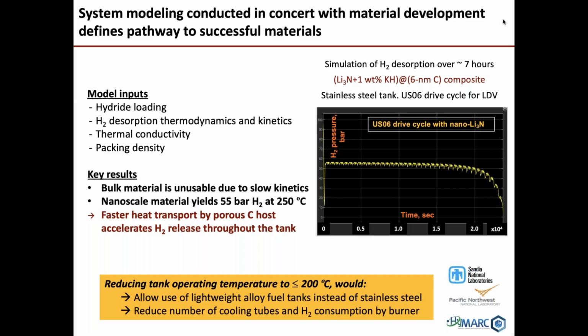Alternatively, if you take the nanoscale material, it has a much higher thermal conductivity because the hydride is trapped inside of the pores of this carbon. And the porous carbon essentially is graphite, which has a very high thermal conductivity. And what we find under those circumstances is that we can start the fuel cell and it will run at a stable pressure of 55 bar, assuming an operating temperature of 250 degrees C. So right away, what this tells us is just looking at the simple arithmetic of how much hydrogen is in a material is not enough. You have to take a more comprehensive view of how the hydrogen interacts with the entire system.